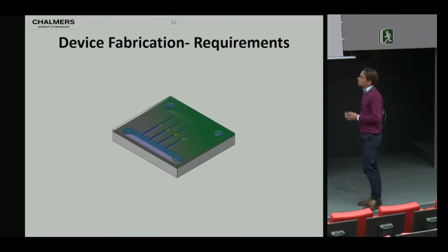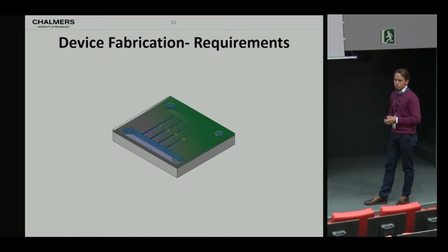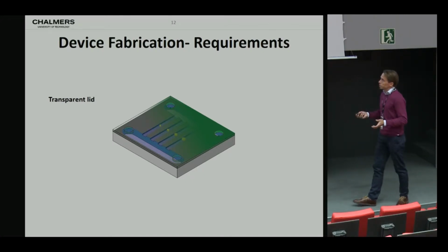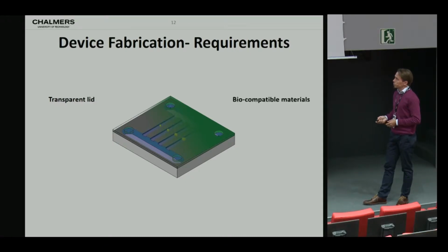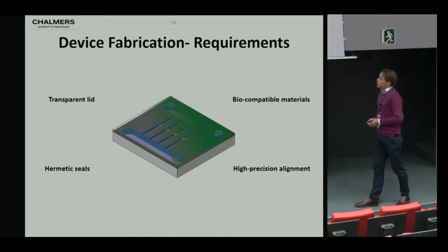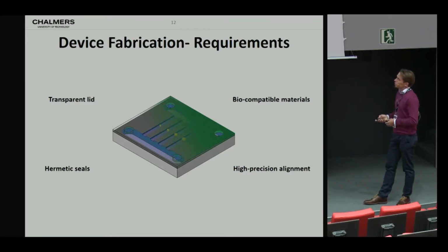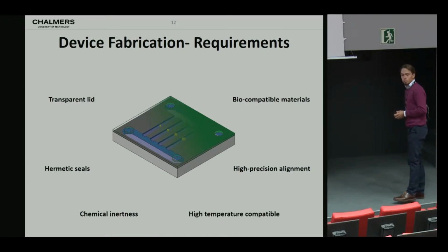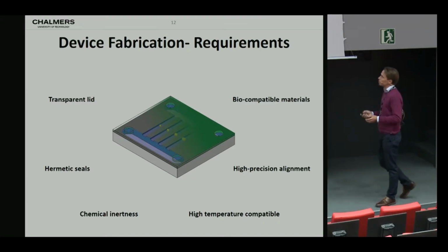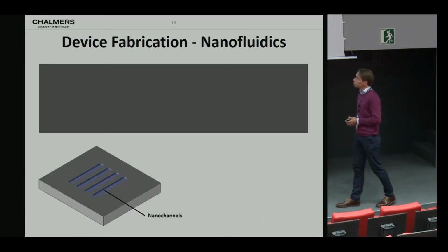Before I explain that, I would like to pin down a couple of requirements that we have for this to work for our purpose. The first one, of course, we need a transparent lid, otherwise we can't do spectroscopy in the visible range. It should be biocompatible materials. We need very good sealing between the lid and the channel structures, because leaks will basically make the device unfunctional. We need high precision alignment to be able to place the particles in the channels. We want this to be chemically inert, and for catalysis, we also want it to be high temperature compatible. So this is quite a number of requirements that we have to fulfill. So how do we do it?